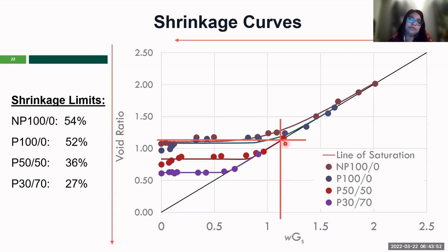So two important things to look for here: a non-polymer 100% sample, which is these darker points here, shows the highest shrinkage limit, so 54%. And for the 100% sample, the polymer sample showed early deviation. So you can see from these points here, this is early deviation from the line of saturation. So these are the two key things that we can see. And this early deviation is likely due to the residual hydrocarbon present in this sample.